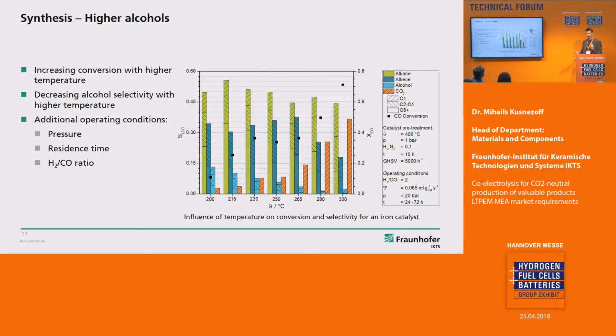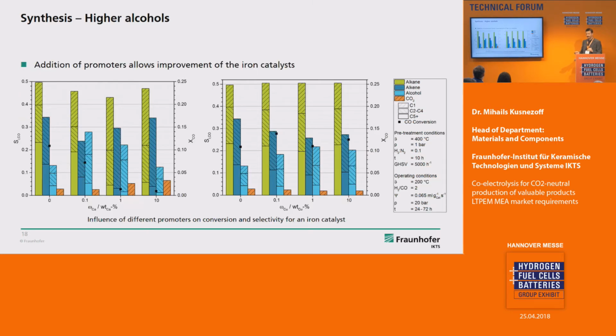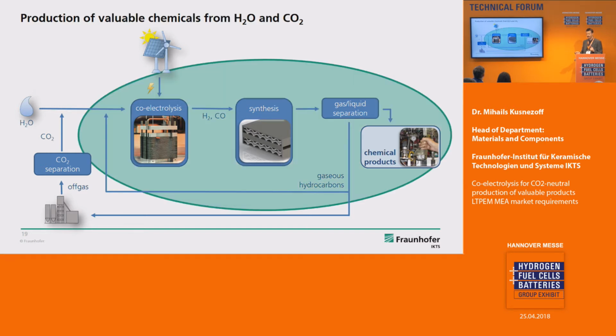It's the blue line. If we dope iron with different additional elements, then we can even increase the selectivity. For example, with doping by calcium, we have higher selectivity. With doping by copper, we have a little bit lower. And these are elements we are playing with. There are also other elements, but it's only to demonstrate in what direction we can move. Now we are speaking about the whole system. And every reactor is important, but they should play together in the whole system to reach high efficiency.